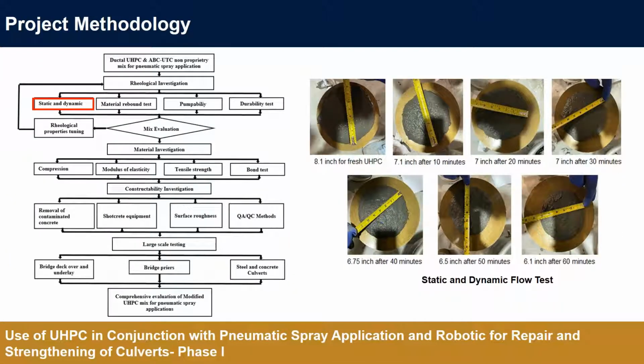Here on the left side is the flow chart that we are using to develop the UHPC for shotcrete. First of all, we have rheology investigation. In this case, we use static and dynamic tests, and we are concerned about material rebound or loss, pumpability, and also whether the mix can be hindered by some durability issues. After that, we have material investigation. We need to confirm that the compressive strength and modulus of elasticity, all those mechanical properties, didn't change much during the process. We also have constructability investigation. We will need to know the removal of contaminated concrete, what shotcrete equipment is suitable for the operation, surface roughness and preparation, as Dr. Azizinamini mentioned in the previous presentation, and some QA and QC methods. And applications vary from bridge deck overhang or overlay or underlay, bridge piers or columns, and also steel and concrete culverts.